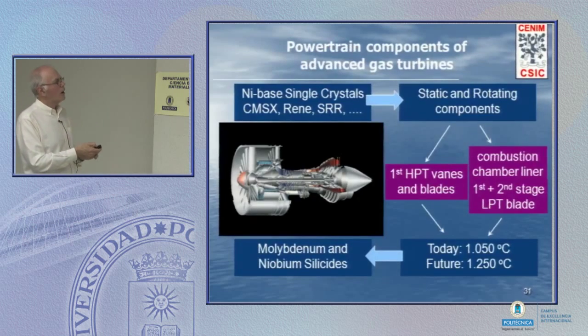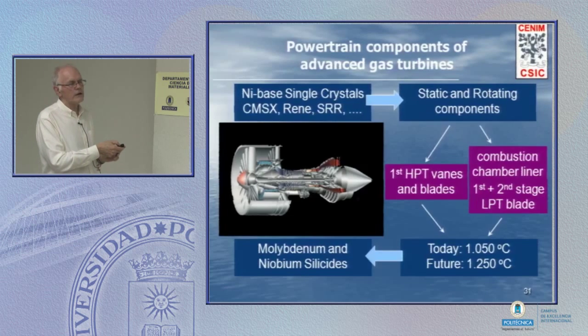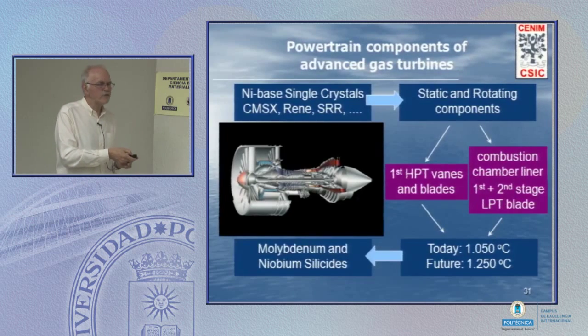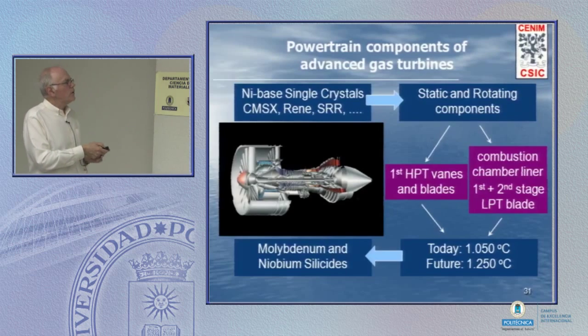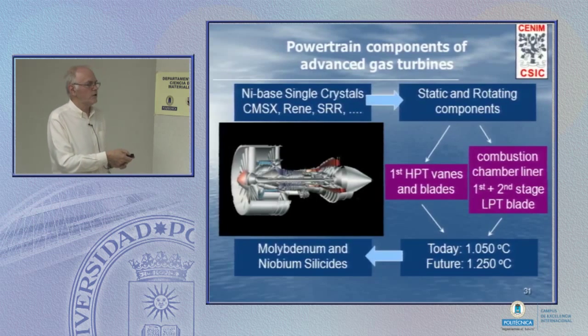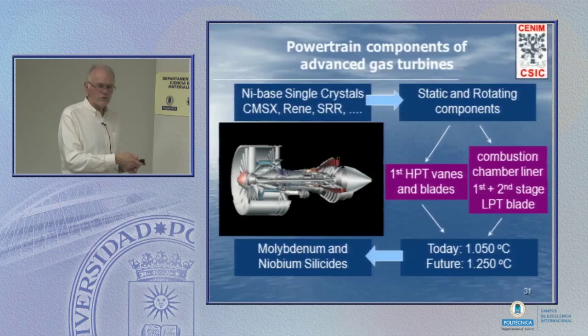Now, what's the interest? The great big success story of gamma prime nickel-based superalloys, perhaps of the cobalt superalloys as well, has been a tremendous success in the hot zone of the jet engine. And these alloys have an upper limit of operation temperature of 1,000 degrees and a little bit more. What the turbine makers are hoping for with molybdenum silicides, or perhaps with niobium silicides, this may be a little bit more British with Rolls-Royce, this may be a little bit more American with GE, is to jump up to significantly higher temperatures, temperatures where superalloys have, if not yet molten, become extremely soft.